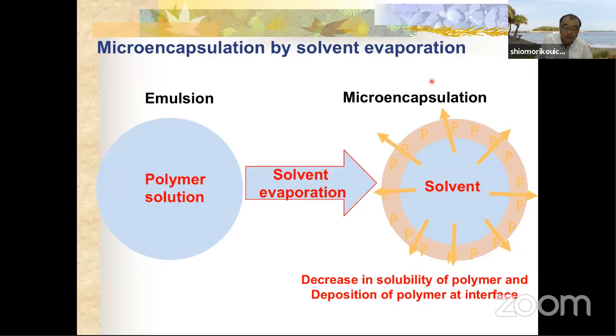The next one is the solvent evaporation method. Polymer is dissolved in organic solvent, after making an O/W emulsion. Then pressure is reduced and temperature is raised, so the solvent is evaporated from the oil droplet. The polymer is deposited at the interface of the droplet to make a particle wall like this.